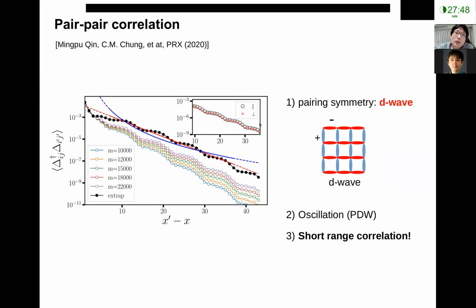This is indeed what we observed in this panel: the black circle is the correlation between vertical and vertical bonds, and the red curve is the correlation between vertical and horizontal bond with a minus sign, an opposite sign. You see that if we apply a minus sign, they become perfectly symmetric. This tells us the pairing symmetry in the system is indeed the D-wave symmetry we expect.